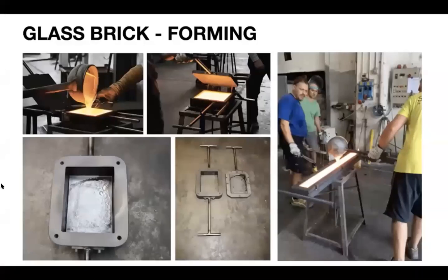Bit more on the glass brick making here. So after the glass is poured into the mold, it is left at an ambient temperature to rapidly cool. This rapid cooling is essential to avoid the molecular structure from crystallizing and turning cloudy. So it needs to cool rapidly so that it can maintain its transparency. The glass is then removed via suction at the top surface and transferred into an annealing oven. The molds are designed with a removable bottom surface so that they can be easily removed at this phase, at the end of this rapid cooling phase. So here you can see some of those glass bricks being formed there in the molds. And here you can see a solid glass lintel for the project being formed as well.